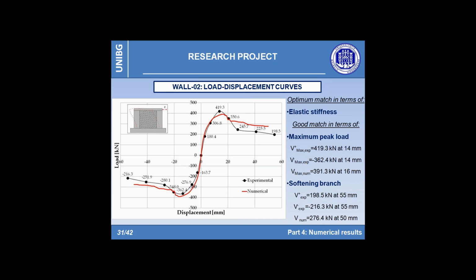The maximum load, equal to 391 kN, was reached for an imposed drift of 0.58%. This represents a mean value between the maximum and minimum peak load observed experimentally, respectively minus 7% and plus 8%, compared with the higher positive and negative value of the strain capacity observed imposing a drift equal to 0.5%. This confirms that the contribution in terms of stiffness and strength due to the presence of an infill plays a key role for the correct modeling of the seismic behavior of the tested structure.